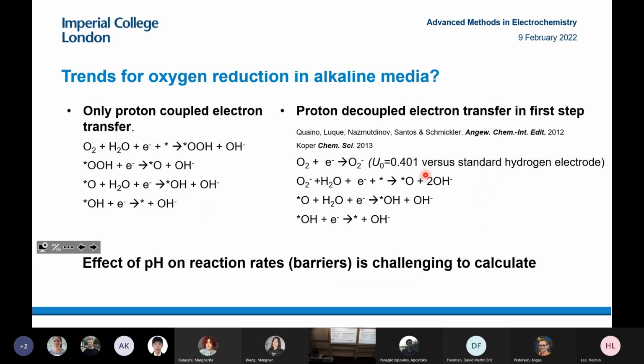And some people have proposed that some surfaces, especially gold, are much more active in alkaline media because you have a slightly different reaction mechanism. You don't go through these proton-coupled electron transfers, you actually make a superoxide species. And when you go very alkaline, the potential required to do that would be much more positive on the reversible hydrogen electrode scale. And this is maybe why relatively inert catalysts, because you overcome this initial step, which is a limiting step on gold. You can actually overcome this if you work in alkaline media.